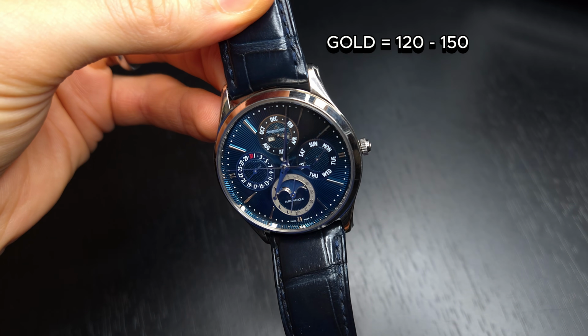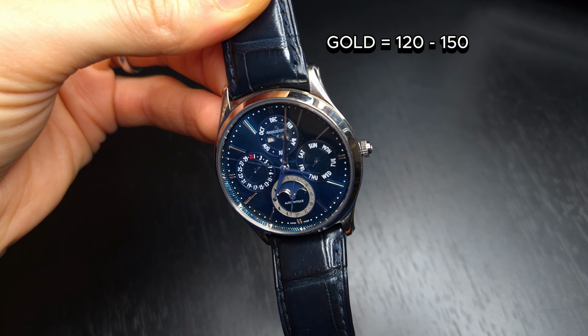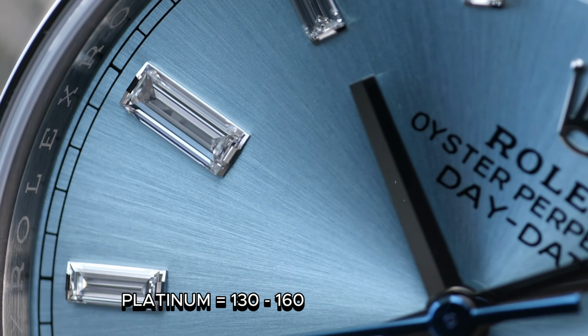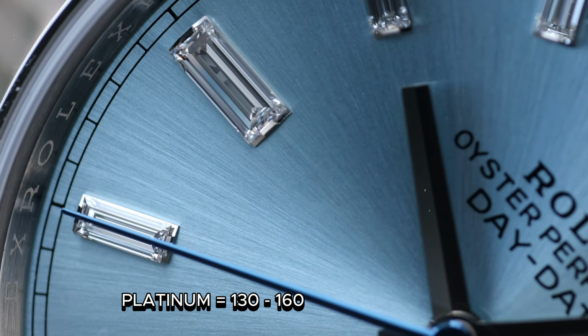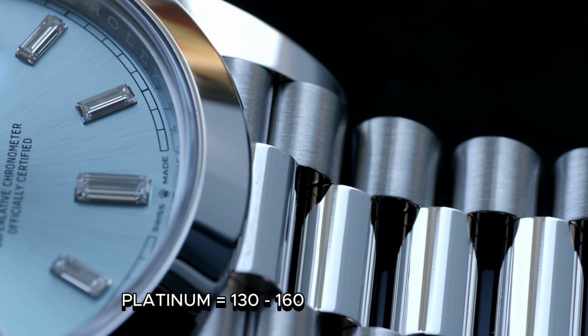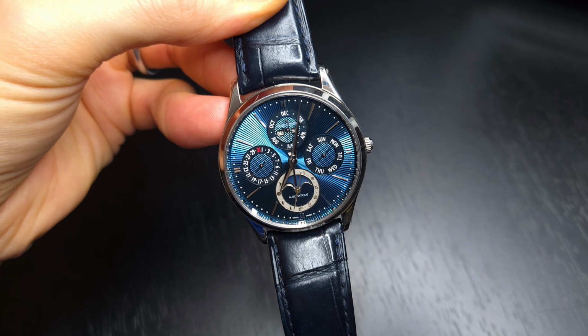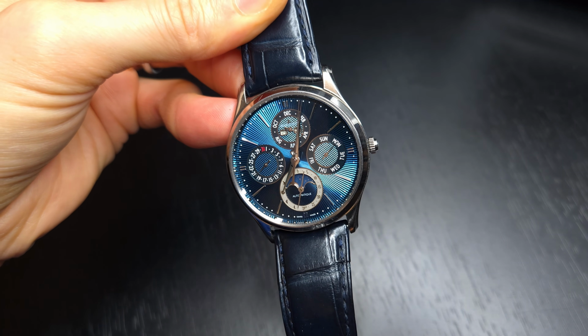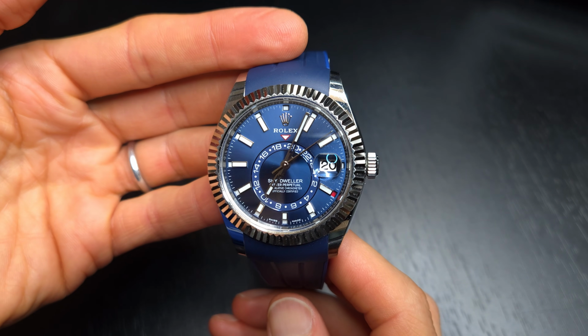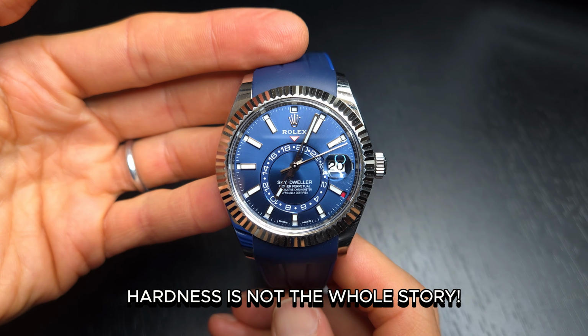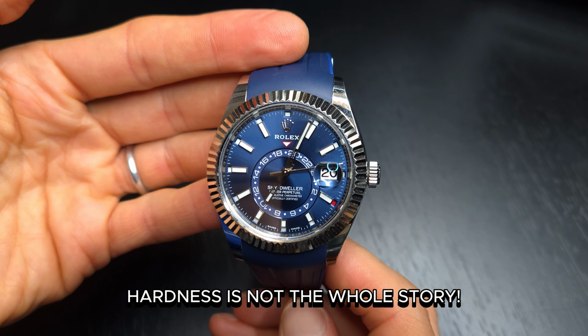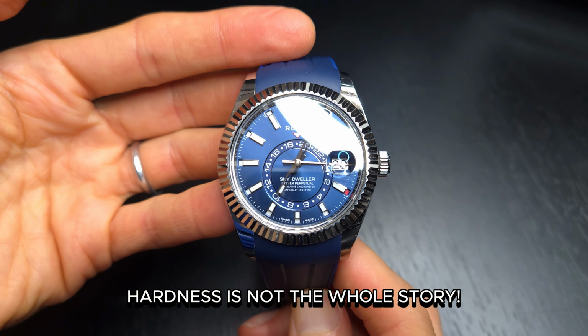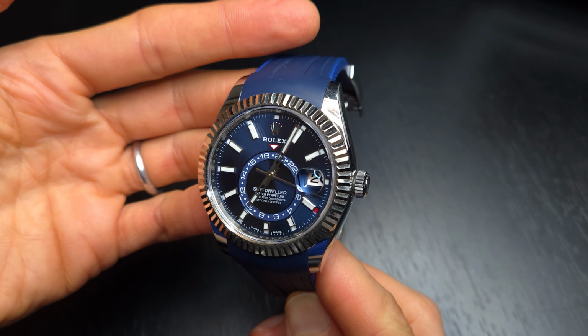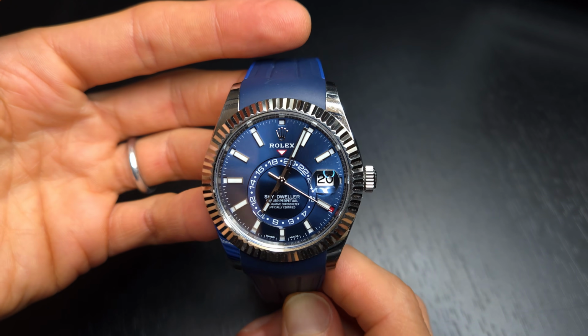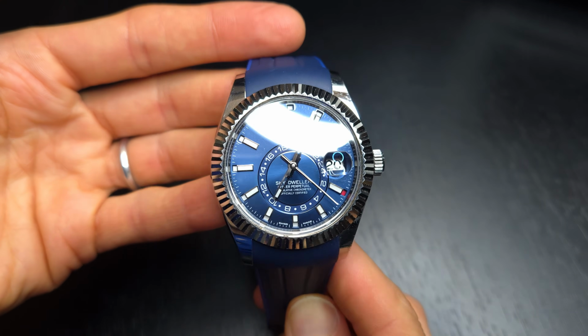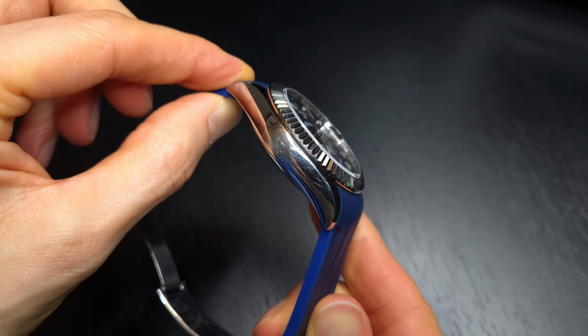And then with gold, you'll get around 120 to 150 Vickers, with platinum being just slightly stronger, around 130 to 160 Vickers. So yes, some materials are objectively more scratch resistant than others. But here's the key point of all this. Hardness is not the whole story. A harder material can still show scratches, and a softer material might wear more gracefully. And finishing plays a massive role in how wear actually appears on a watch.